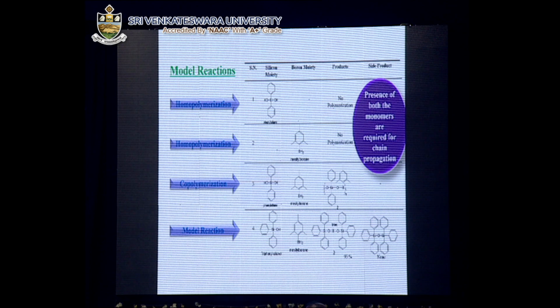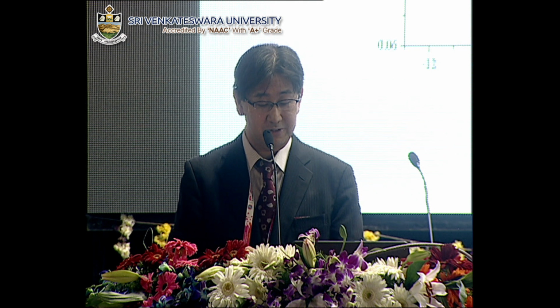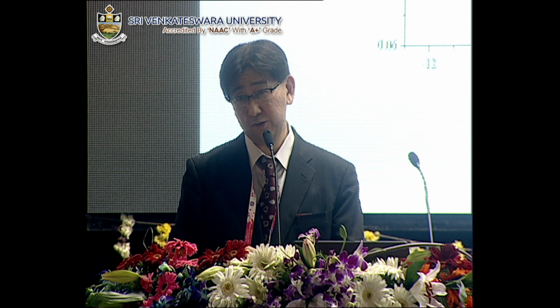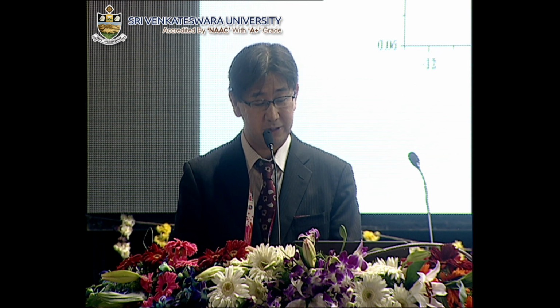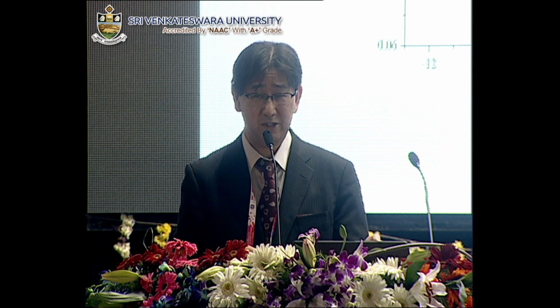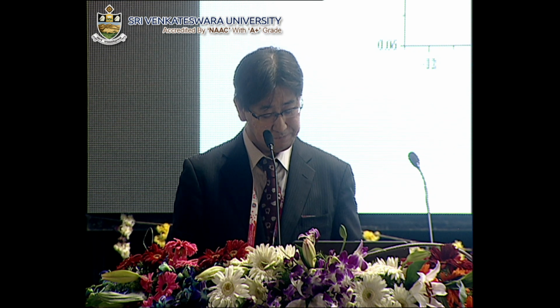Okay, and the final topic is the novel polyborosiloxane. This polymer is also a novel material, and it is also found to show very high sensitivity to fluoride anions. As you see, this polyborosiloxane shows sensitivity even to 10 to the minus 10th molar concentration of fluoride anion in aqueous systems. As far as we know, this is the lowest detection limit for fluoride anion ever reported. DFT calculation indicates that in this polymer structure, boron is exposed to the outside of the polymer chain, so such a conformation should be responsible for the extraordinarily high sensitivity to fluoride anions.